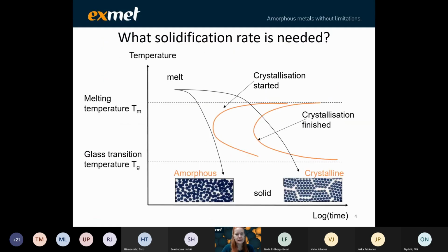And being a material scientist again, I'm interested in what solidification rate is needed to achieve this amorphous structure. It can be described looking at a temperature and time diagram like this one, where we can see, as in any common material in the normal crystalline world, we have crystallization noses, where the crystallization starts and finishes as a function of temperature and time. And the solidification rate that is sufficient to create amorphous material is at such a quick rate that it passes ahead of the crystallization noses.